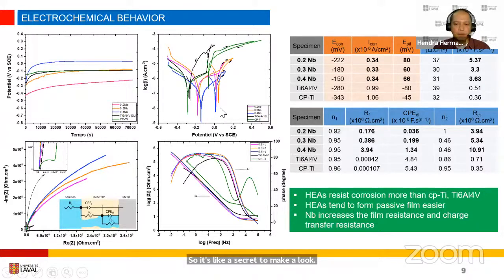Okay, and from that we can obtain some important parameters. And then we did some electrochemical impedance spectroscopy to characterize the dielectric behavior of the passive film. From here we can obtain its corrosion potential, everything compared to Ti6Al4V and also to commercial pure titanium. And as we can see, the high entropy alloys have lower corrosion current compared to these two titaniums, and high pitting potential, meaning it is difficult to induce pitting on the surface of these alloys.